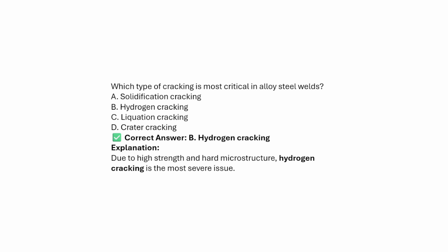Next, which type of cracking is most critical in HSLA welding? Solidification cracking, hydrogen cracking, liquation cracking, or crater cracking? The answer will be hydrogen cracking, because due to the high strength and hard microstructure, hydrogen cracking is the most severe issue. Hydrogen cracking is nothing but cold cracking or delayed cracking. Okay.